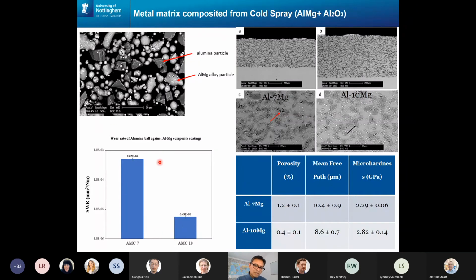This is just to give you an idea of their performance. Wear rate wise, specific wear rate, we are around 10 to the minus 4, and for this one is around 10 to the minus 6. So they are significantly better than just the pure metal or just the pure ceramic.